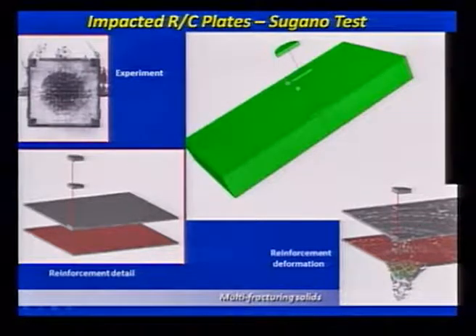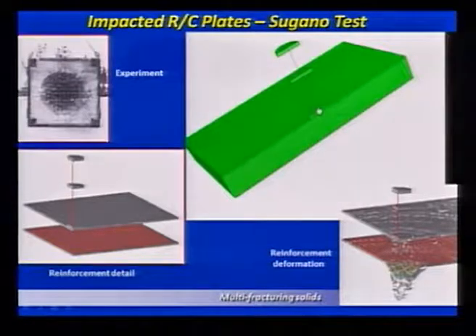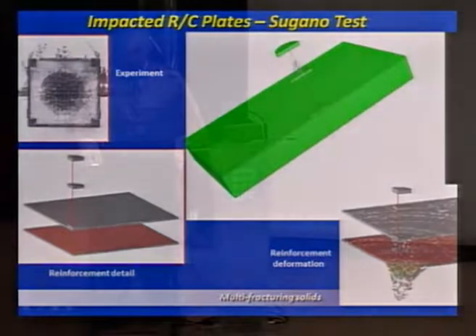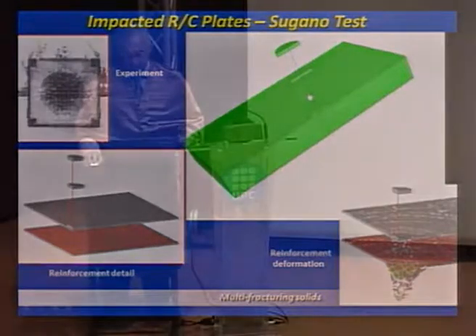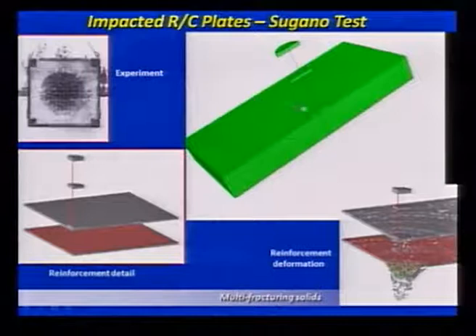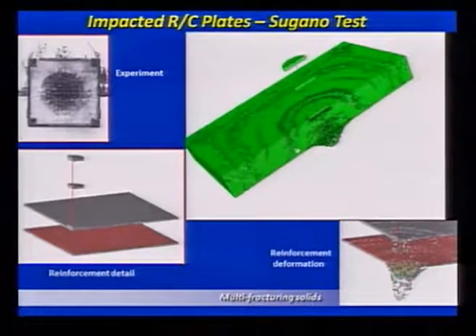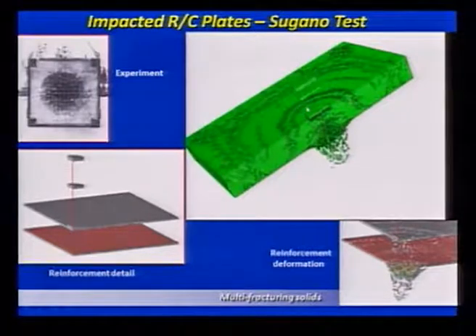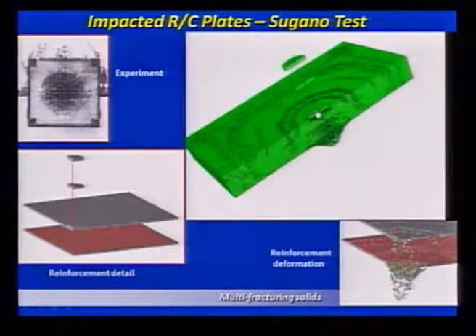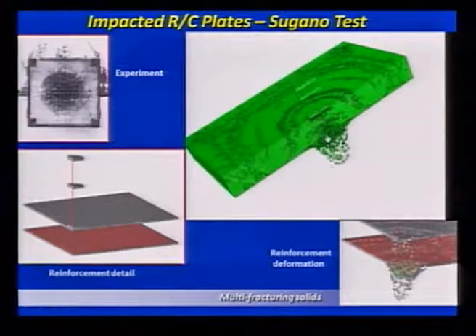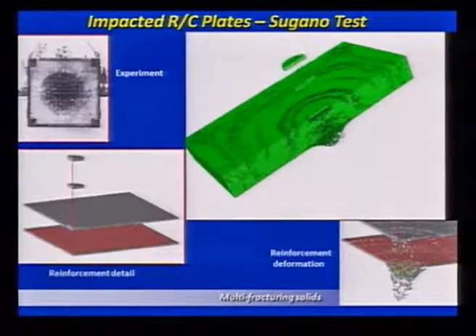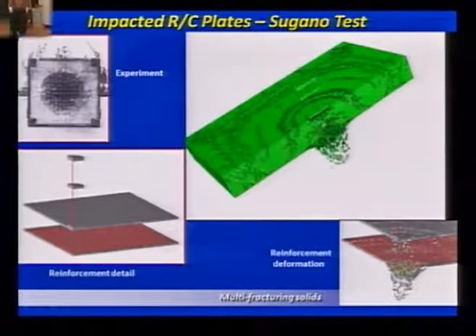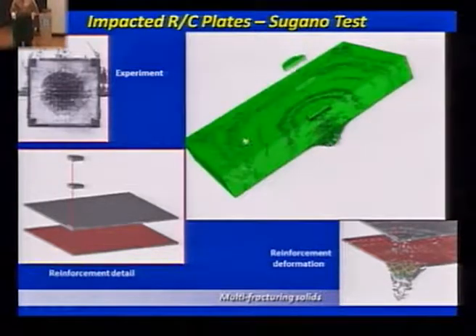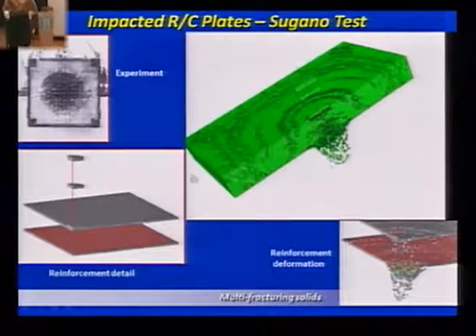It's impacted by these three masses, which are meant to represent a jet engine, and on a spring, which is meant to represent the casing of the jet engine. And essentially, what you can model is this kind of behavior: first of all, a compression wave is just reflected as a tensile wave, and then this causes a fracture around here, and then you get these series of fracture rings that occur.